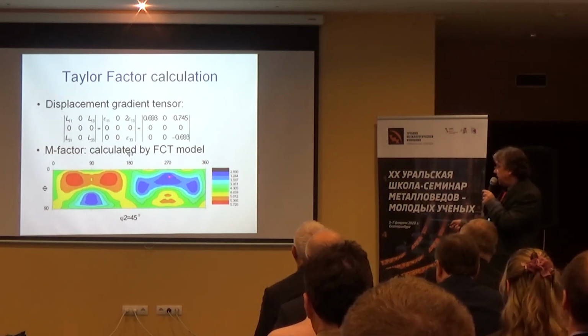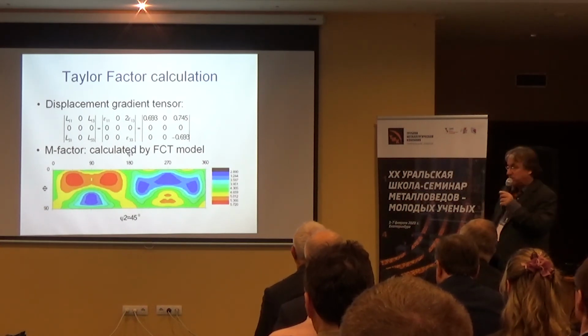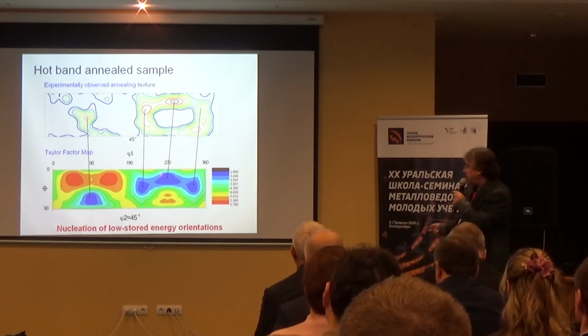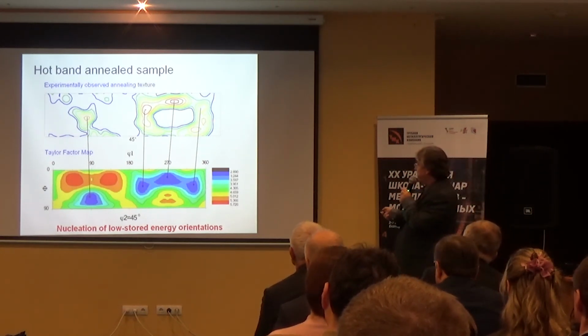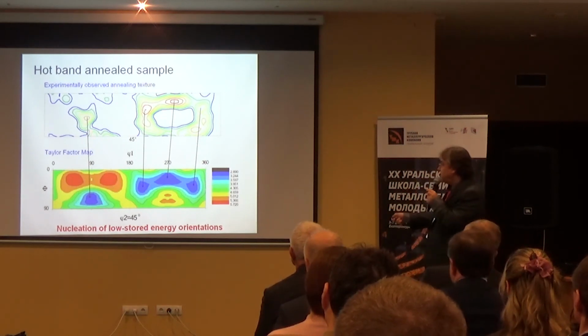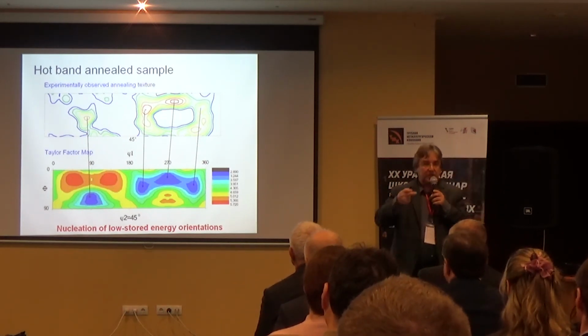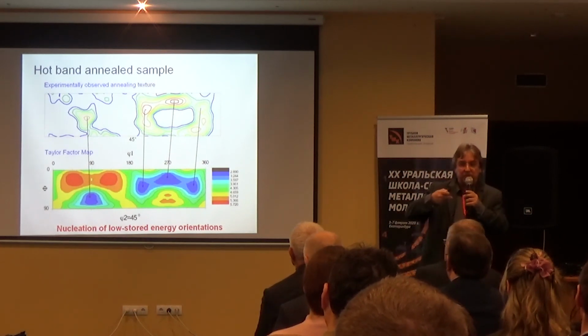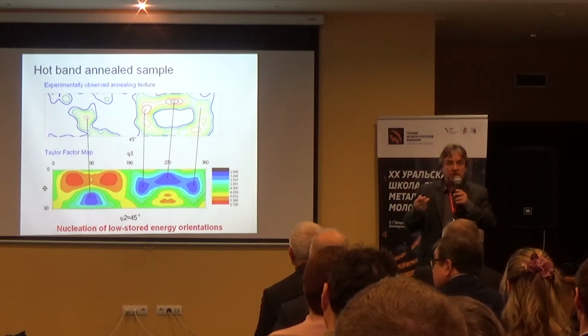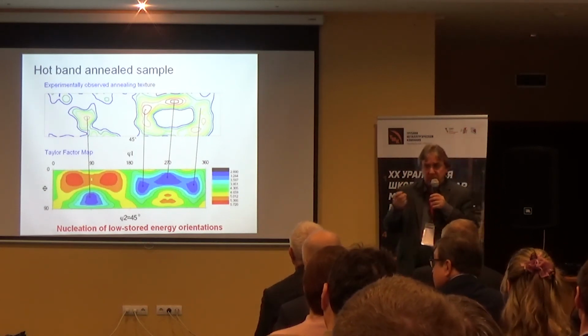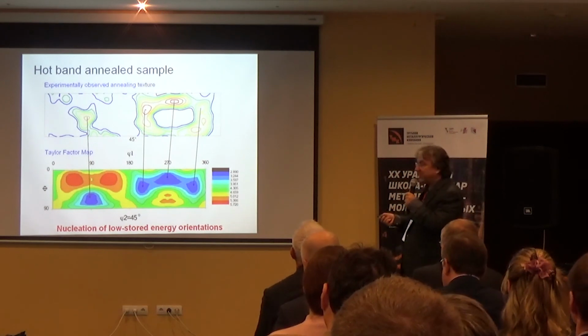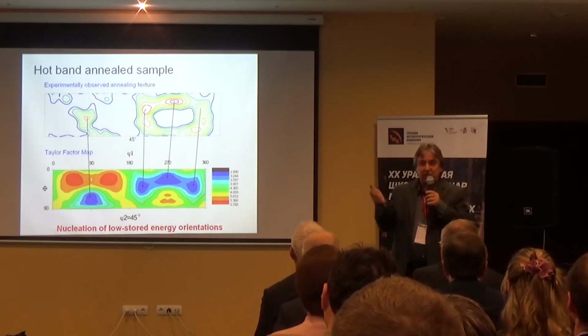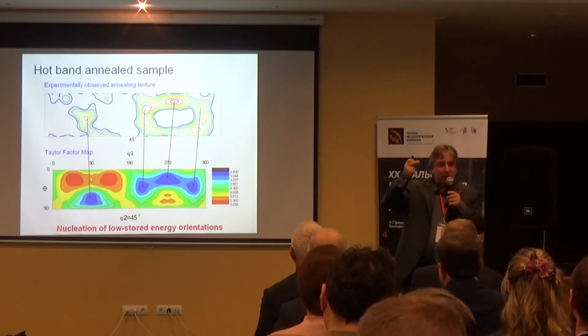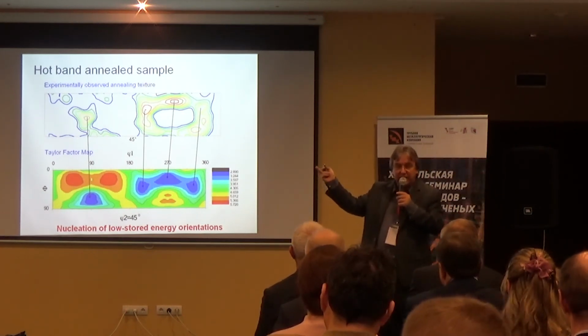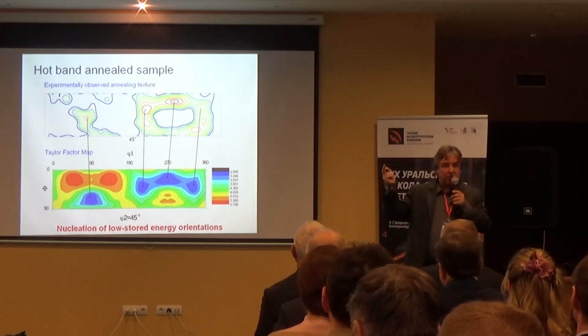You see here that in this blue region, we have low stored energy grains. And it is quite peculiar that in this case, the maximum of the texture corresponds with the minimum of the Taylor factor, whereas in the previous example, it was just the opposite. And what was different between the two examples? Well, the strain mode was different, but I think more important, the temperature of rolling was different. Here we were rolling at elevated temperature. By the way, this steel, at the temperature that we rolled, was still in ferrite because of the silicon content.